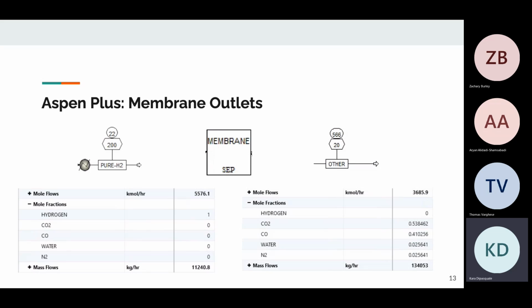From the stream labeled other, the components are displayed as they are released from the membrane. These components include carbon dioxide at 54 molar percent, carbon monoxide at 41%, and water and nitrogen gas both at 2.5%. These components were simply unable to pass through the palladium membrane and act as waste components. A waste analysis will be computed to determine the best possible solution for dealing with the waste stream.